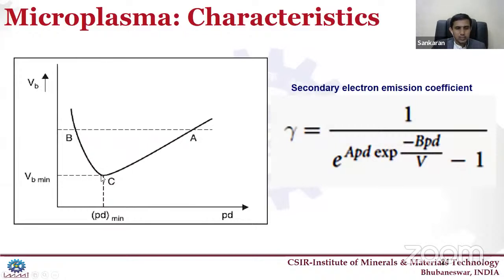With the increase in the applied voltage, the distance between the anode and the cathode, and the change in the pressure, the breakdown voltage changes. From that, we can calculate the secondary electron emission value. When you change the pressure and the distance, the breakdown voltage changes, as well as the voltage we are supplying. According to those values, you will get the secondary electron emission coefficient values.